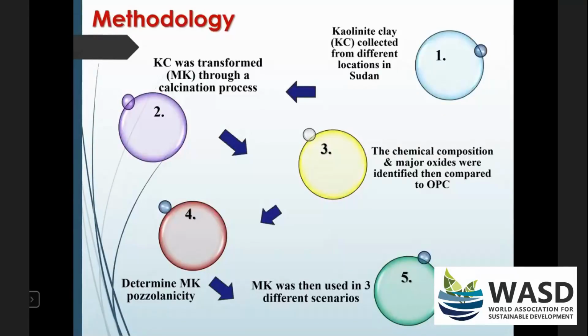So the methodology that we basically adopted was as follows. The kaolinite clay was collected from 4 different locations in Sudan for this study. And after that, we transformed the kaolin clay to metakaolin through a calcination process. Then we checked the chemical composition to determine the major oxides available in this form of material, and compared that to ordinary Portland cement. As well, we wanted to determine the degree of pozzolanicity for this new material before using it in different ways in concrete mixtures.